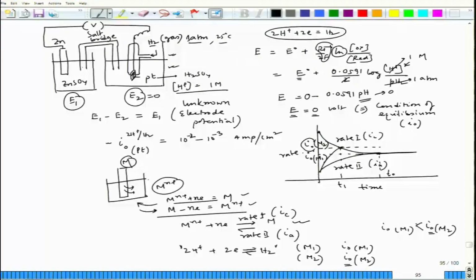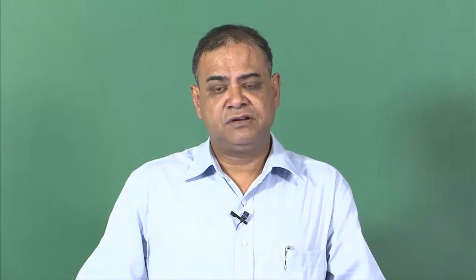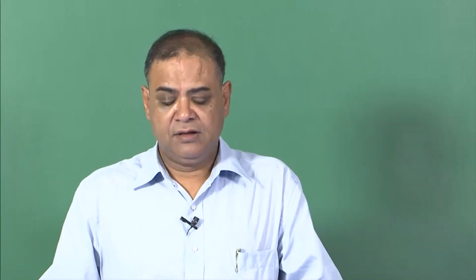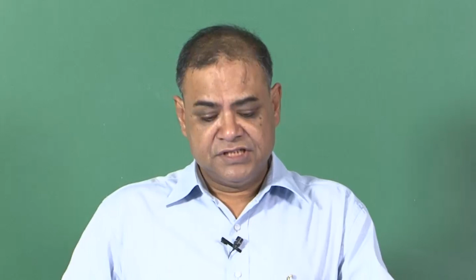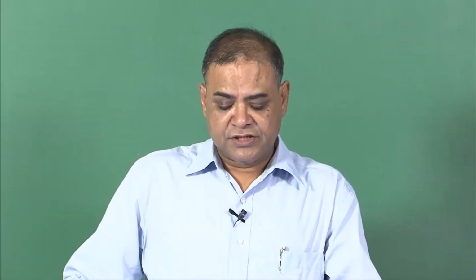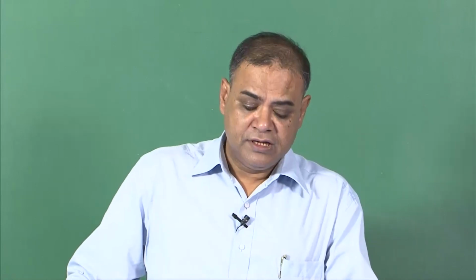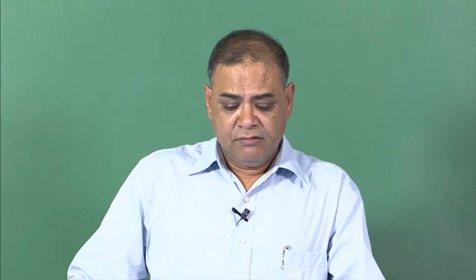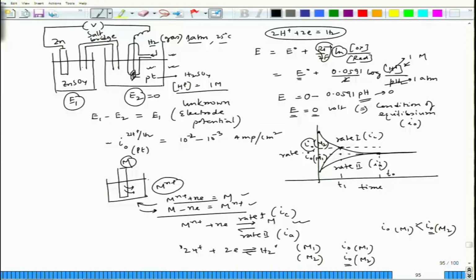re-established quickly. So, all the time we can maintain this standard reduction potential to be at the known potential. So, it will help us in determining the reduction potential or the electrode potential of some unknown cell. And there could be possibilities that that equilibrium is disturbed by some means during the measurement of this unknown electrode potential. And since platinum has a very high exchange current density of hydrogen reaction, it will re-establish the equilibrium, and so we will be okay with this reference electrode.